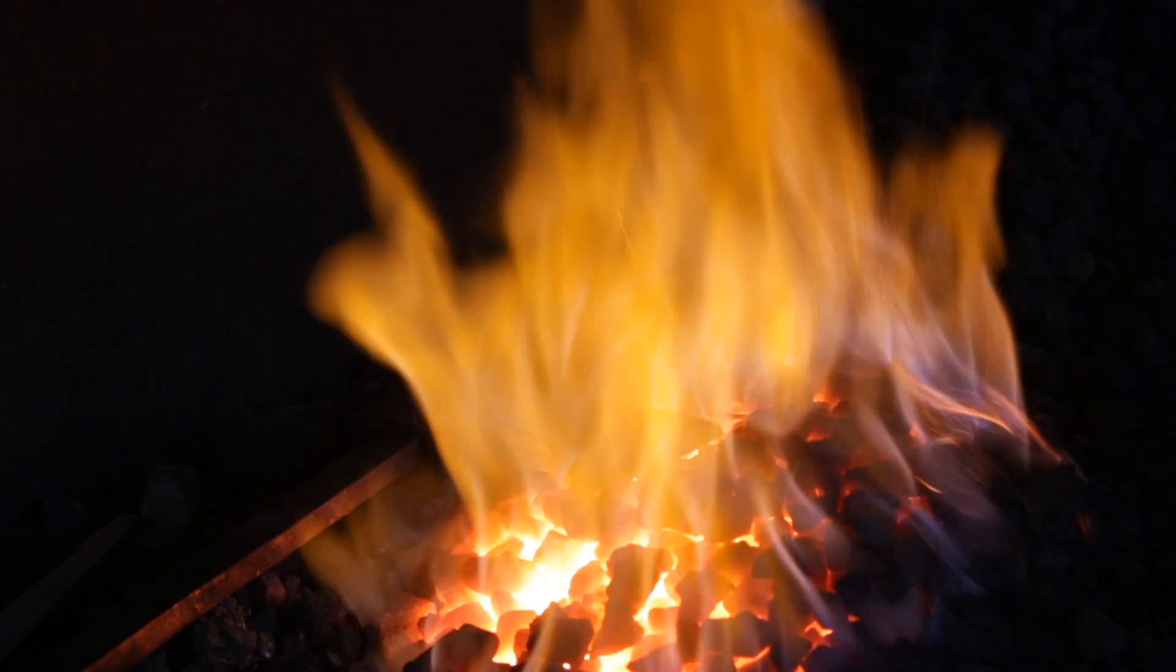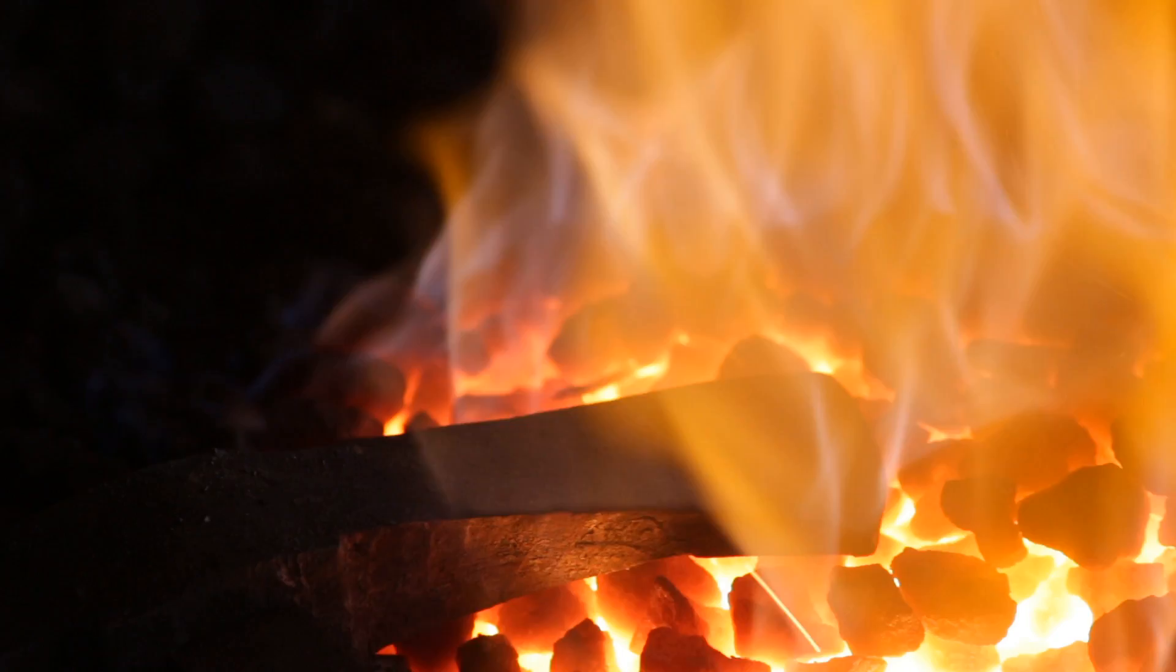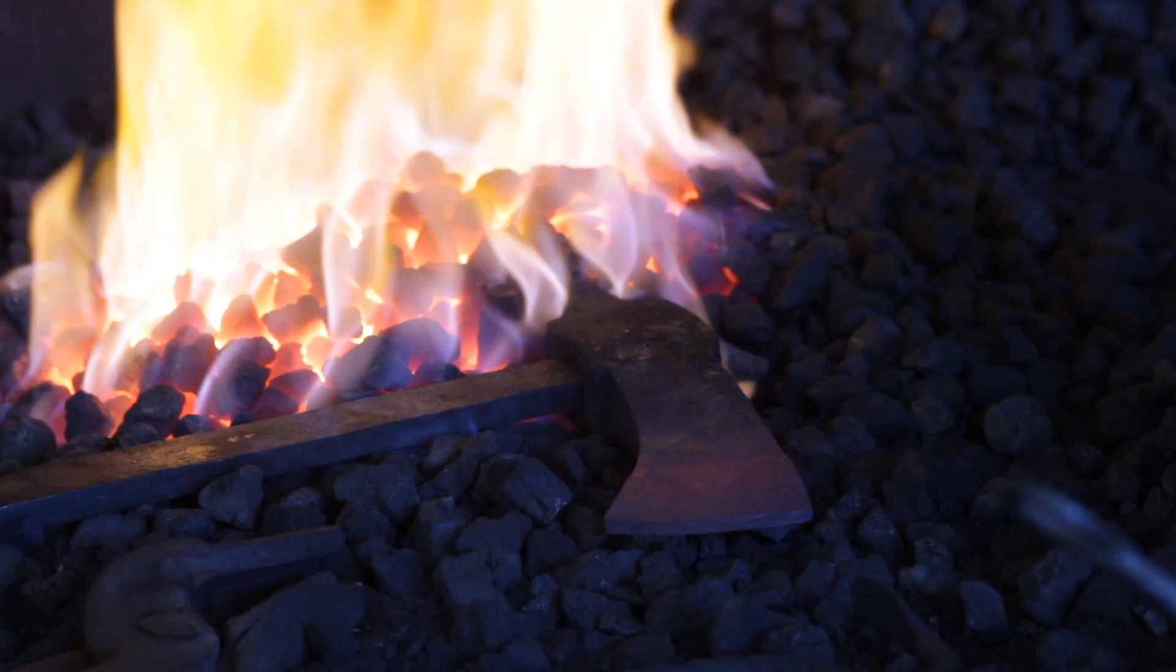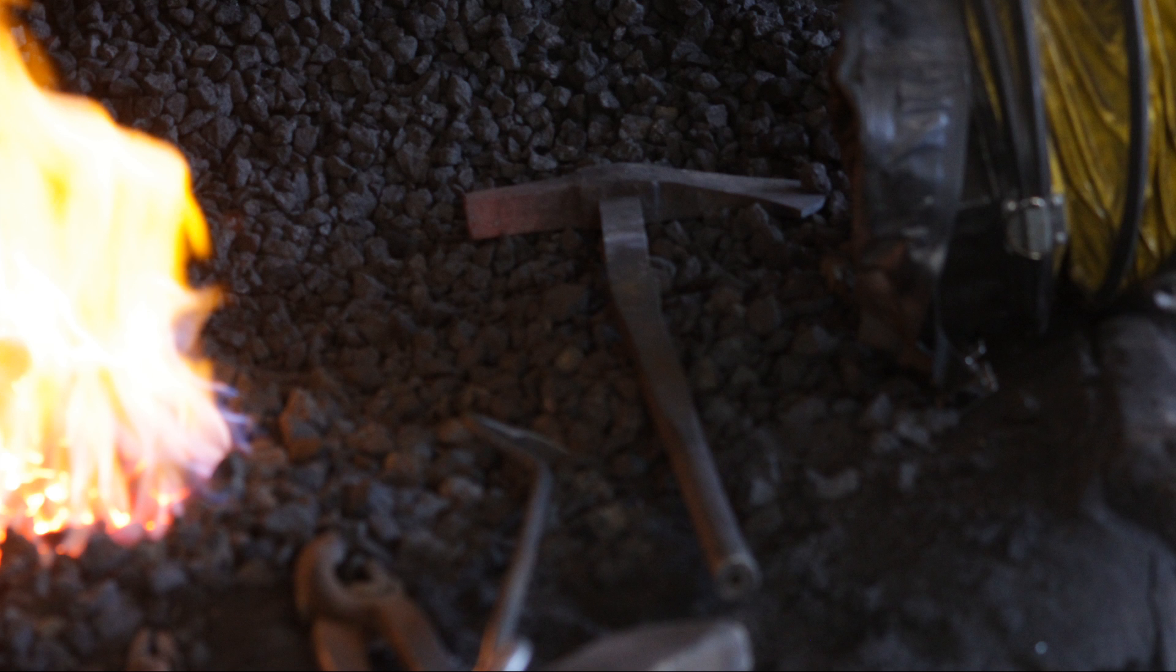And at this stage I decided to normalise the blade. Now I don't want to normalise the whole thing because I don't want to loosen the rivet. So I just sat it on top of the fire to normalise the carbon steel insert on the blade and on the hammer head. And once it had bypassed the curie point I've set it to one side to air cool.